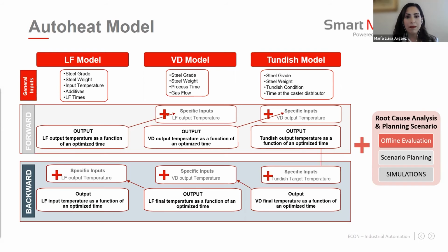For each stage, 7 machine learning models were compared, among which are random forest, nearest neighbor, artificial neural network, and support vector machines. Each model was evaluated with the model performance metric, which is the mean absolute error, MAE, and the model with the minimum MAE was selected. Also, the same models were applied using principal component analysis, PCA, on the features, analyzing if the mean absolute error was smaller than without this transformation, in order to decide whether or not to apply the PCA.